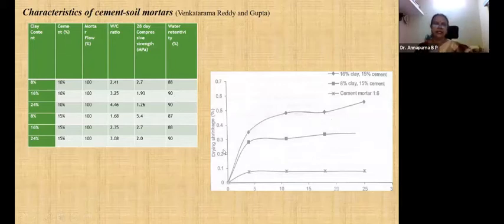And this is the drying shrinkage. With cement mortar 1:6, the drying shrinkage is less. But with 8% clay and 16% clay, both with 15% cement only, this is for 8% clay and this is for 16%. So with increase in the clay content, the drying shrinkage is also increased. So we can see this is the drying shrinkage.